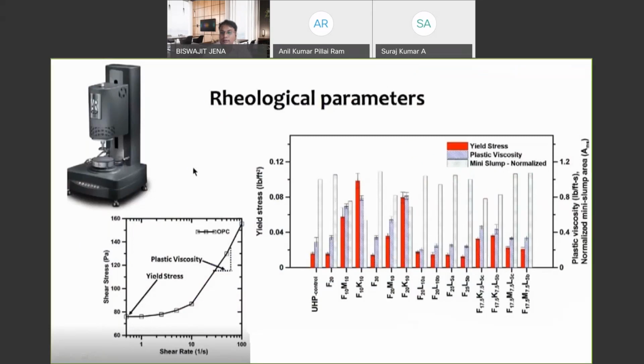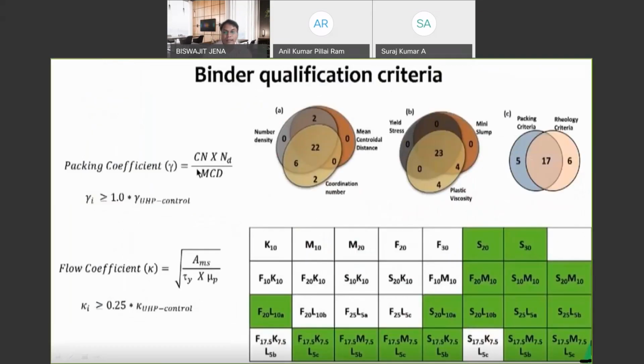So to design such mixes, having yield stress and plastic viscosity measured using a rheometer is very expensive. So we'll go for a mini tool, a simple tool, that is the mini-slump. So do a mini-slump flow and we will get the rheological parameters. Next, using these two parameters, I can show you that we have done 33 mixes.